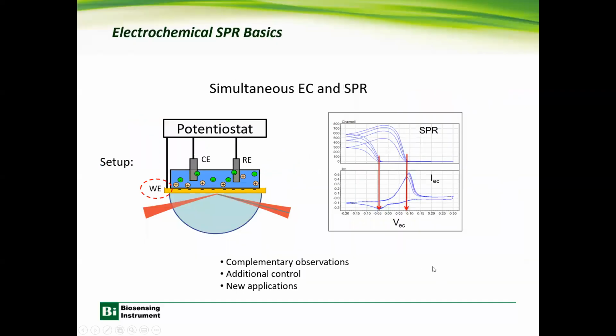So when you combine electrochemistry and SPR and put them together, now you have electrochemistry, with which you can control the process happening at the surface, and SPR, which can determine or measure the physical conditions of the interface. Therefore, you have complementary observations by combining the two, and also added control parameters. And with this, you have a further degree of freedom to design new applications.